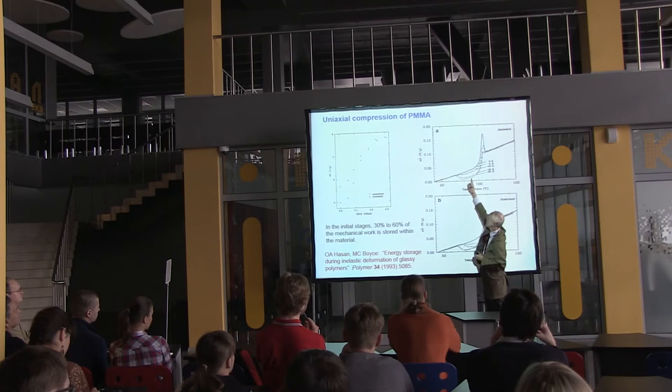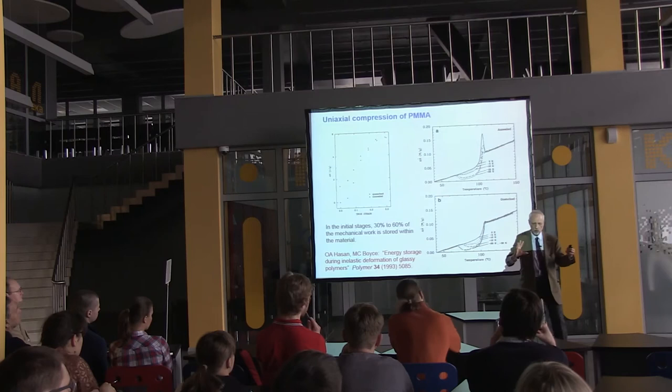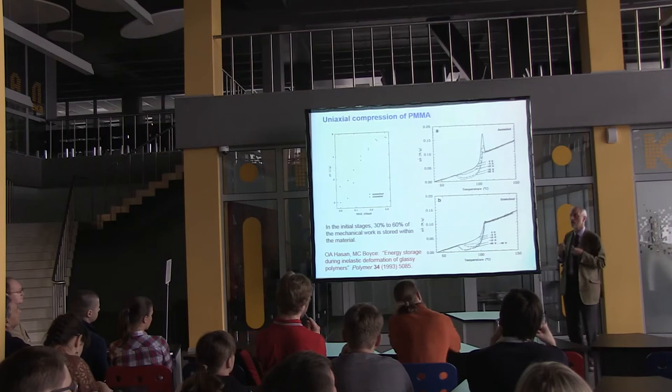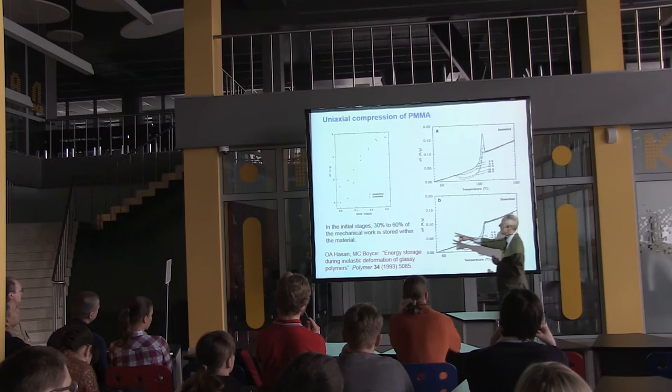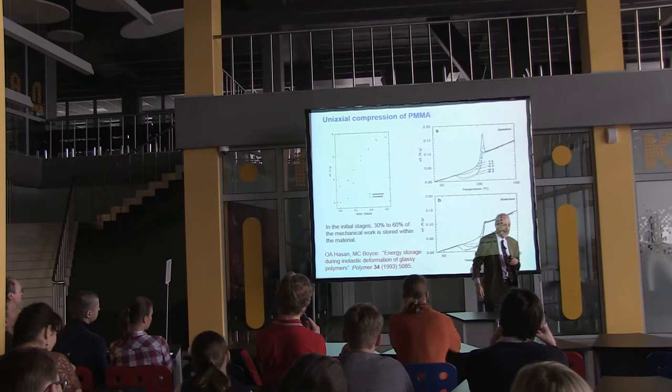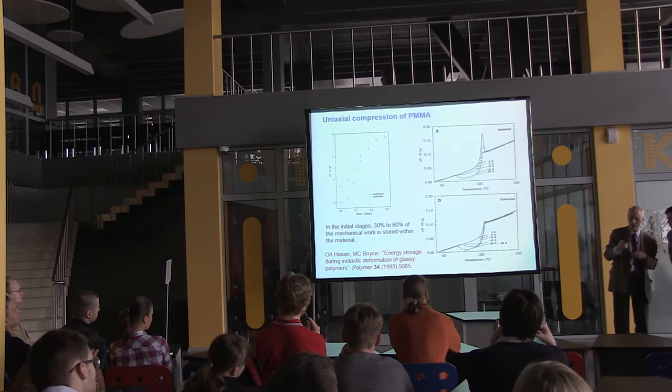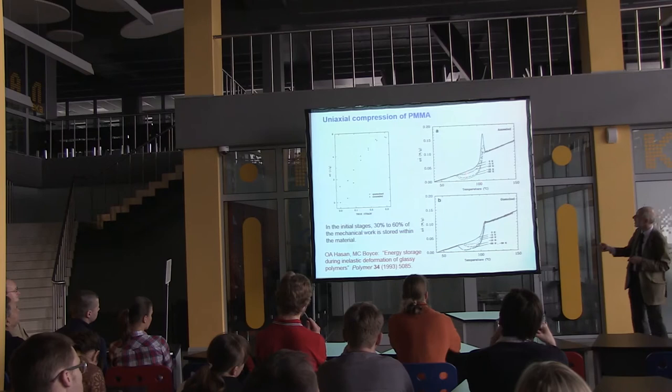When you do mechanical work on the polymer you can ask how much of that energy remains stored inside the material. The answer is a lot — perhaps 30 to 60 percent of the energy is stored in the material. This area under the calorimetry curve is the stored energy, and it relates to the amount of mechanical work done.